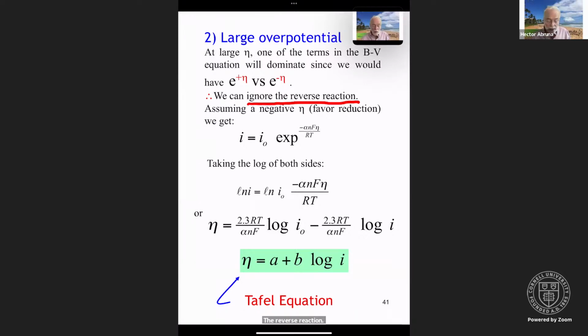Okay. And so if we assume a negative overpotential, that means we favor the reduction, then we get that I equals I0 e to the minus alpha NF eta over RT. If we take the log of both sides, ln of I equals ln of I0 minus alpha NF eta over RT, or we can rearrange this as eta equals 2.3 RT over alpha NF log I0 minus 2.3 RT over alpha NF log I. This is usually expressed as eta equals A plus B log I, which is known as the Tafel equation. And so the Tafel equation derives from the Butler-Volmer at large overpotentials, because we have a large enough overpotential that we can ignore the reverse reaction.